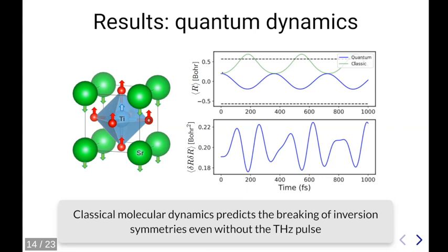While if we do the classical limit of the equation, so only the Newton equation, and we evolve them, we have a completely different dynamics, which is off-centered with respect to zero, the paraelectric phase. We obtain a fake ferroelectric phase because classical dynamics doesn't account for the quantum fluctuations.